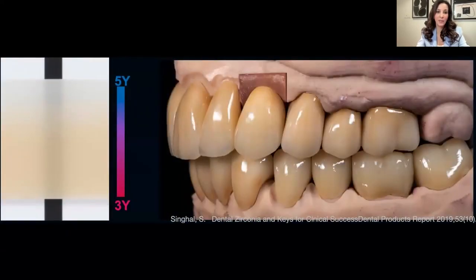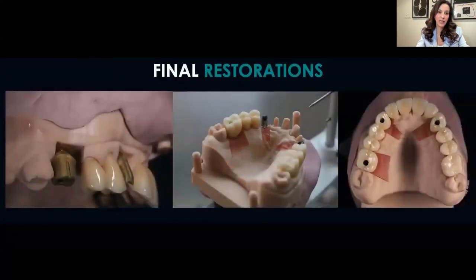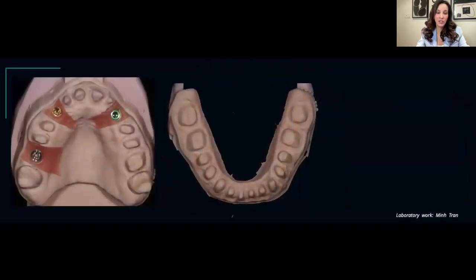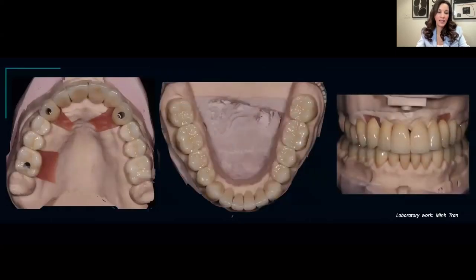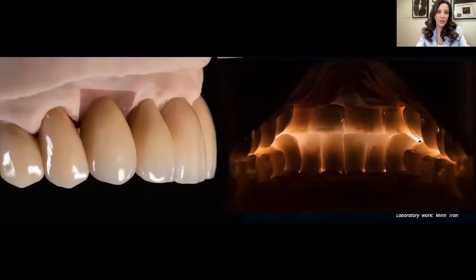And this is an example of one case of full mouth reconstruction that we did using this material. And you can appreciate that we restored the anterior and posterior restorations, as well as the implant supported restorations using this material. And these are the digital scans that were derived, and the models were printed, and the restorations were milled out of this Zircad Prime zirconia, and the case finished with a really beautiful outcome with the translucency as well as the strength. This particular patient had a very strong parafunctional habit.